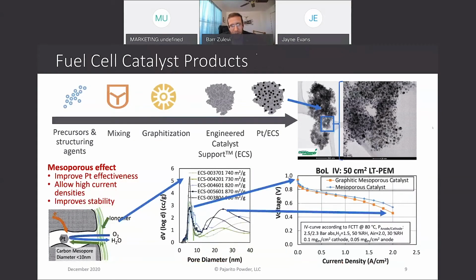So I'll walk you a little bit through our fuel cell product. We make our carbon supports from the bottom up. We design them, which is an alternative to currently used commercial commodity carbons. We make our precursors and structuring agents, which include, of course, niobium. We mix them together in a proprietary approach, as I mentioned, using this Veraform platform. We graphitize them. We then end up with this engineered catalyst support that utilizes what we call the mesoporous effect that improves platinum effectiveness and allows high current density and improves stability.